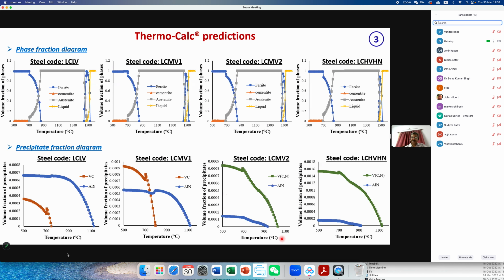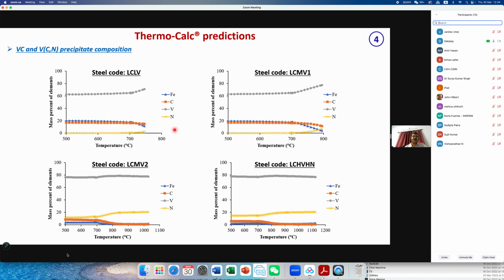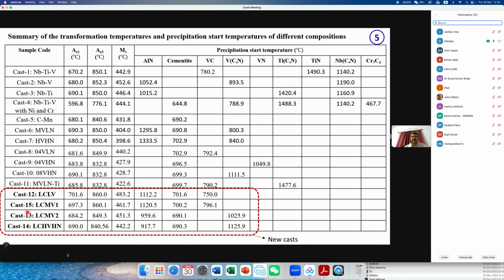We have done the Thermo-Calc prediction of precipitation: at what temperature the precipitates are forming, vanadium precipitates, and what is going to be the fraction of those precipitates. So all the thermodynamic and kinetic calculations have been done initially. And you see here that for all these tasks that we are working on, the precipitation start temperature and transformation start temperature, Ae1, Ae3 during cooling, Ms, all are reported in a single slide.